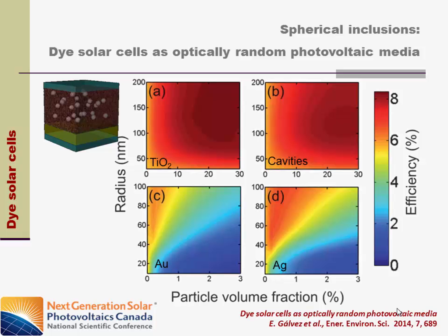What I've been showing you are all the calculations that we do considering that we have isotropic scattering. Why? Because most of the commercial phases that you can obtain in the field are polyhedral particles with a very wide distribution of sizes, so you cannot have true control over the scattering event. However, if you can work with spherical scattering centers, like the ones I'm considering in this work, then you have very precise control over the way in which light is scattered when there is one scattering event.